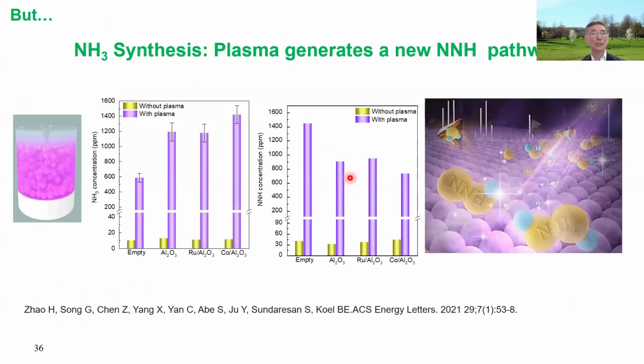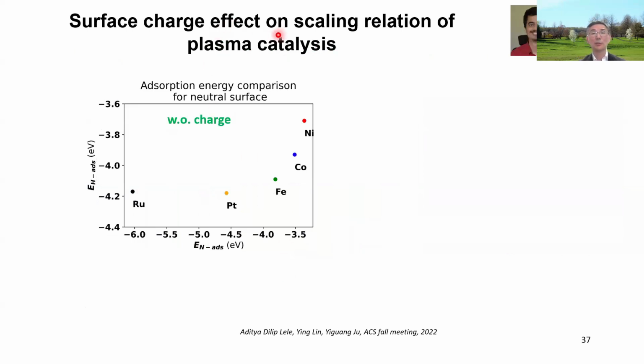So we did some experiments with plasma and different catalysts: aluminum oxide, ruthenium oxide, and cobalt oxide. We found that no matter what kind of catalyst, or even without catalyst, plasma can enhance your ammonia, just because the plasma produces a new NNH pathway, and they form ammonia. And then the question is, what is this story about plasma-assisted ammonia catalysis? Is it NH? Is it N adsorption? Or is it something else? Is there any hope that plasma can dramatically accelerate ammonia production? So my former postdoc, now a professor at Rowan University, I asked him to study how surface charge affects the adsorption and dissociation of hydrogen and nitrogen.